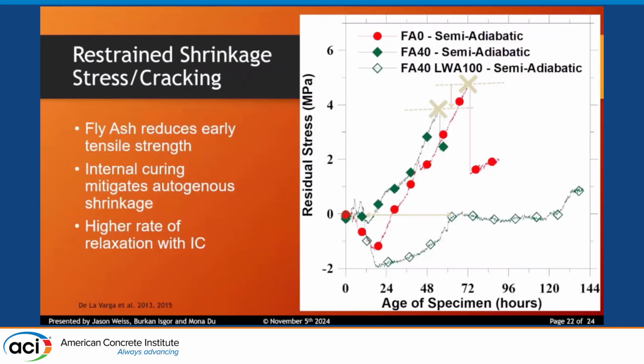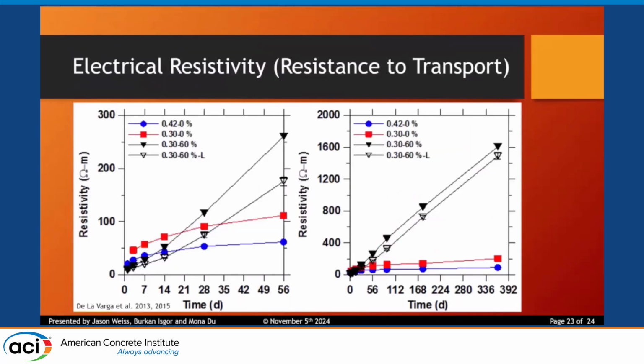If we look at the overall stress that develops towards shrinkage cracking, again, conventional system where we've just replaced the fly ash, where we've put in internal curing, we're getting no tensile stress developing in the overall system. The additional benefit that comes from this is now we can start to plot things like the electrical resistivity, right? And there's lots of people saying, well, this jump has to be because of more reaction. There's a huge nonlinear effect here because once you've filled the capillary porosity, it's much harder for the ions to start moving through the gel pores.